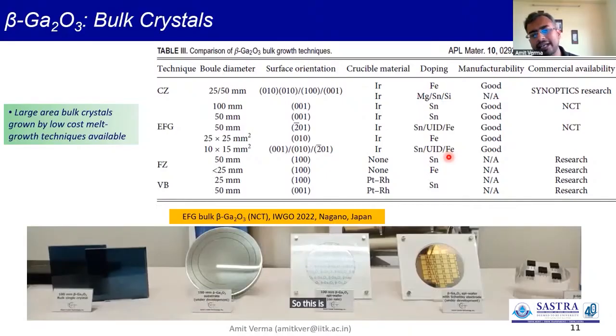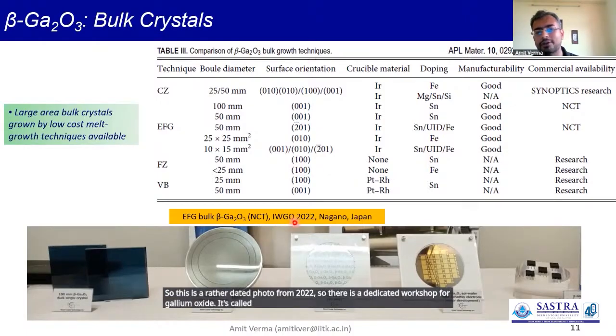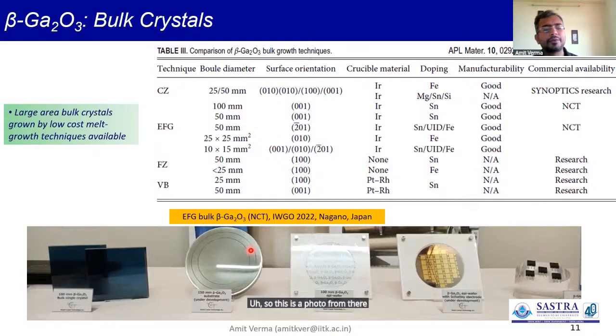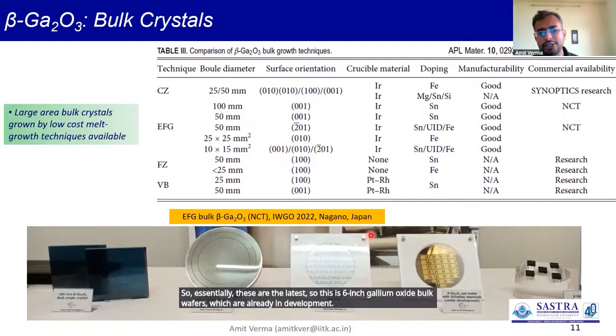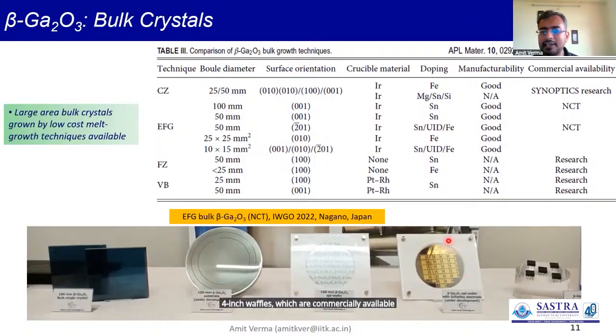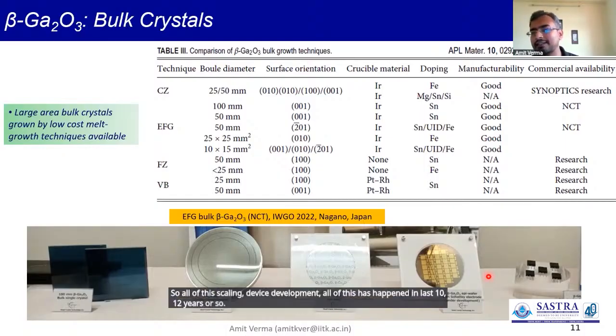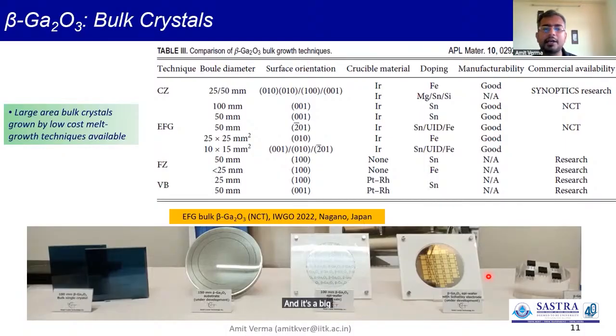So that is one big advantage, which has allowed this. This is a rather dated photo from 2022. There is a dedicated workshop for gallium oxide, called the International Workshop on Gallium Oxide. This is a photo from there, which we were attending. So essentially, these are the latest: 6-inch gallium oxide bulk wafers, which are already in development, and 4-inch wafers, which are commercially available. These are big Schottky diodes fabricated on the full wafer, and these are diced and packaged devices. All of this scaling and device development has happened in the last 10, 12 years or so. So it is very fast development, and it's a big community that is now contributing to this.